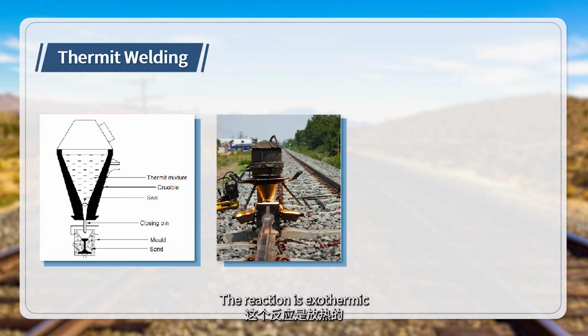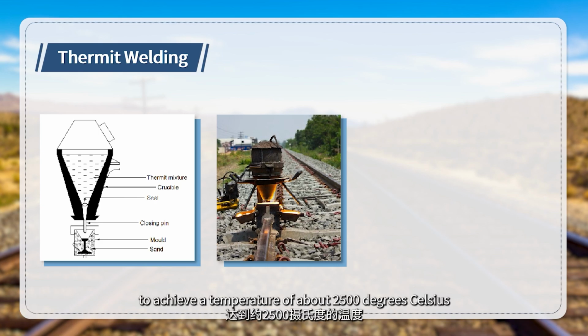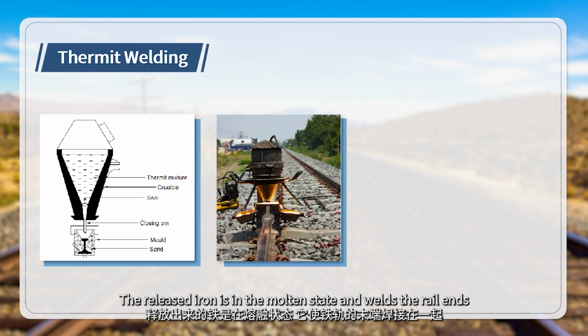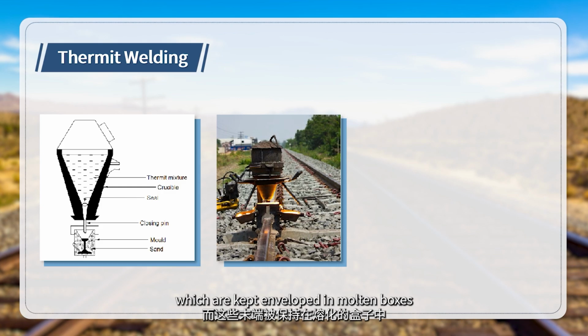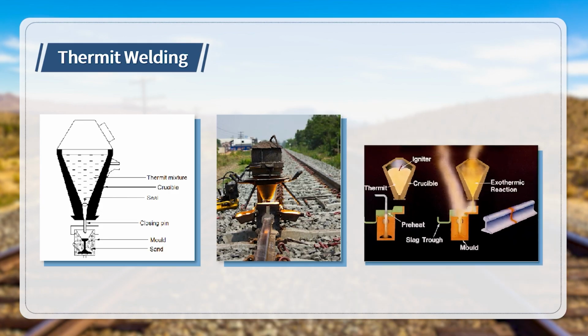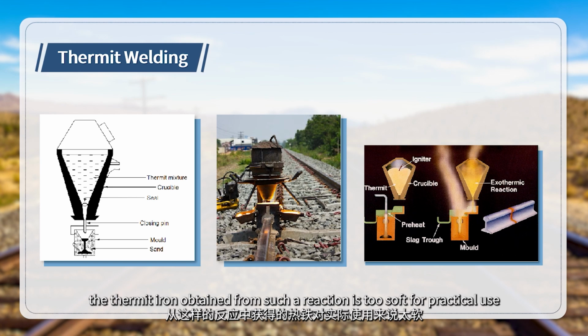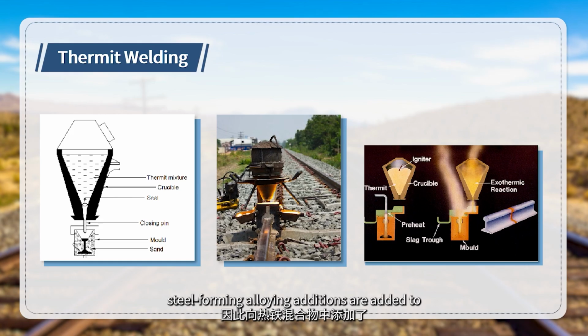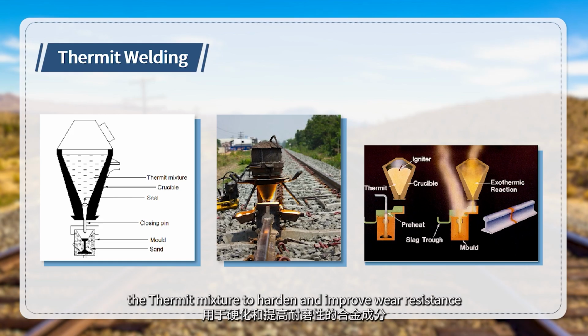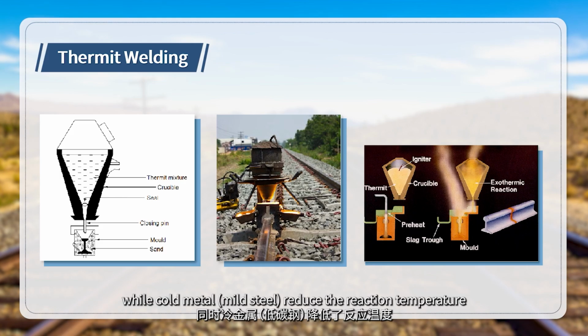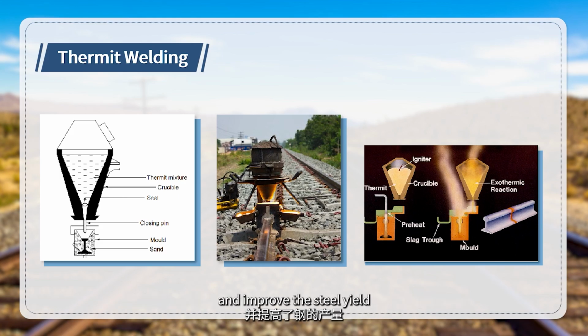The reaction is exothermic and it takes about 15 to 25 seconds to achieve a temperature of about 2,500 degrees Celsius. The released iron is in the molten state and welds the rail ends, which are kept enveloped in the mould boxes. The aluminum oxide, being lighter, however, floats on the top and forms the slag. Because the thermite iron obtained from such a reaction is too soft for practical use, steel-forming alloying additions are added to the thermite mixture to harden and improve wear resistance, while cold metal reduces the reaction temperature and improves the steel yield.